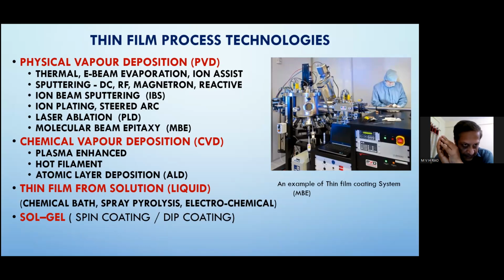So that is a simple method, you can do the discharge using DC. DC means you use a simple DC voltage of up to say 500 or 1500 volts. That is the typical voltage. But that's okay for metals. If you want to deposit insulators or dielectrics, with DC the cathode will slowly get charged. I mean, it will collect the charge and it will not work. So we need to put in RF, oscillating energy. That's why RF. But there also, the RF sputtering rate is very, very slow. Even in the DC case it will be very slow other than for metals.